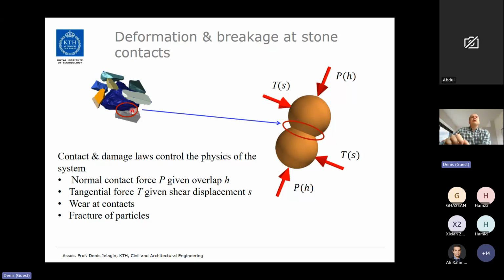We are trying to capture this contact configuration, which exists inside real material, let's say one stone with very complicated surface in contact with several other stones. But we want this particular contact, for instance, here, to behave exactly as our two-sphere contact pair. So we need to define laws which provide us a relationship between normal force, P, applied to the two particles, and overlap between those two particles. We also need tangential contact law, tangential force T, and shear displacement S. And we also need the particle damage laws with respect to wear at contacts and fracture of the particles.